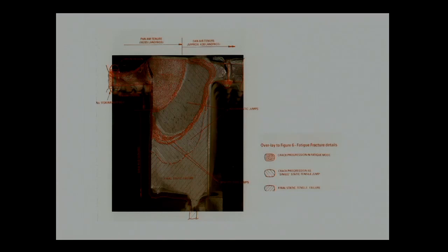As we said before, we have the crack initiated at this point, right? And then you have fatigue crack growth up to that point. In this case, this airplane actually was operated by Pan Am until then. So the crack was already quite large, but was not detected, and then they either got acquired or sold to Dan-Air. So Dan-Air essentially inherited an airplane that already had quite a lot of fatigue damage.